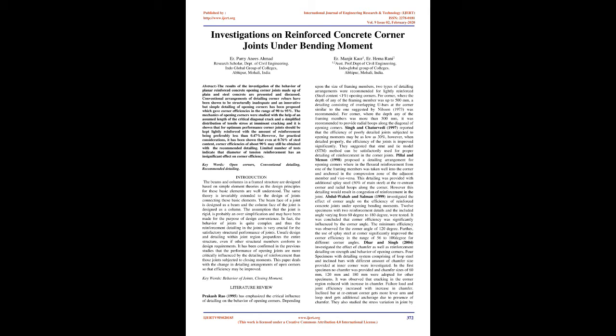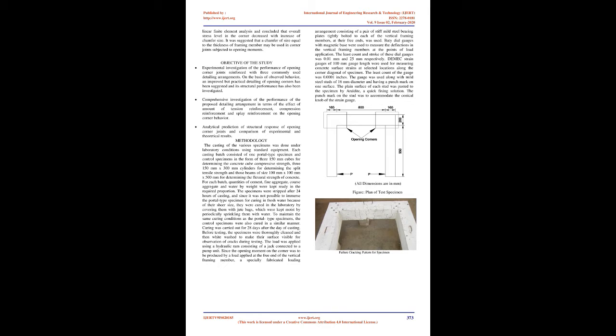Literature review. Prakash Rao, 1995, has emphasized the critical influence of detailing on the behavior of opening corners. Depending upon the size of framing members, two types of detailing arrangements were recommended for lightly reinforced, steel content 1%, opening corners. For corners where the depth of any of the framing members was up to 500 mm, a detailing consisting of overlapping U-bars at the corner, similar to the one suggested by Nilsson, 1973, was recommended.